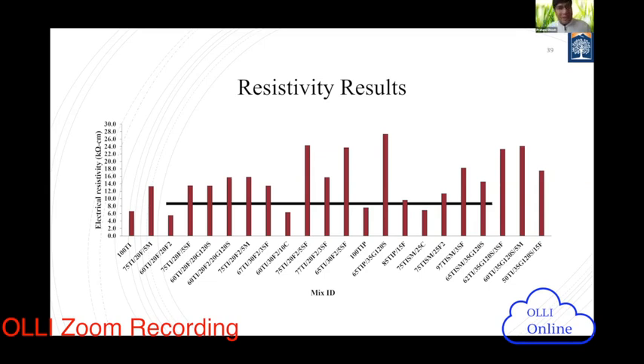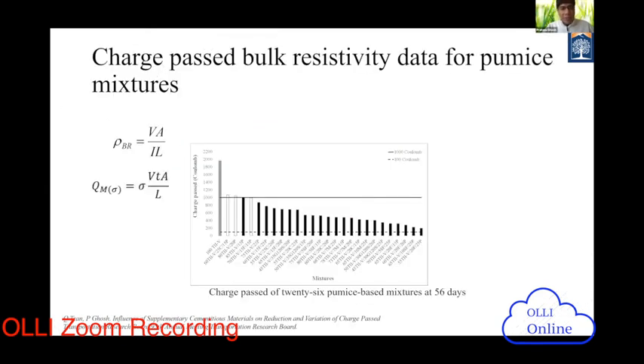We used better materials, sustainable and durable. We tested with better non-destructive emerging techniques, and we got the result value right away. So you do not need to rely on long-term testing. And then we also get charge passed data. Again, you see the charge passed decrease. The values have started to decrease.